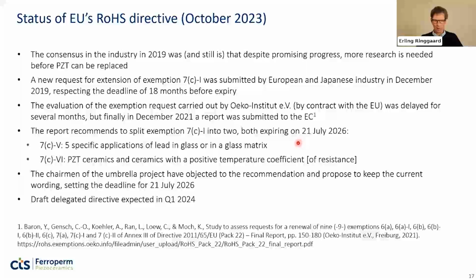It's about glass or glass matrix, and then 7C6 was supposed to be piezoceramics, and then ceramics with a positive temperature coefficient, which is not very precisely written. So I added "of resistance" because the directive is a little bit vague here. Actually, two rather different types of ceramics are put into one here, and one problem with this wording is that there are other lead-containing piezoelectric ceramics than PZT. There are some that do not contain zirconium, for example, so this wording was not so good, and also there were quite a few pyroelectric ceramics containing lead that seem to fall outside this exemption.